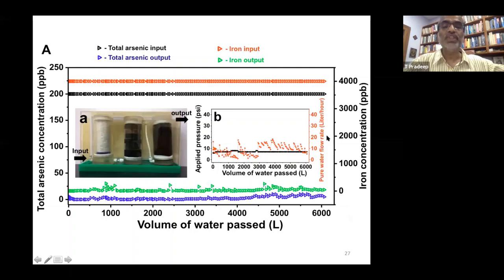And you can do this for larger volumes. So we typically run this for a domestic water purifier of about 6,000 liters. This is to say that for a family, a drinking water requirement is about 10 liters per day. So that is about 3,600 liters for 1 year. We run it for double the quantity, somewhere around 6,000 liters. And that is the input water arsenic concentration, total arsenic input. And this is the output that you have. So it works very well.